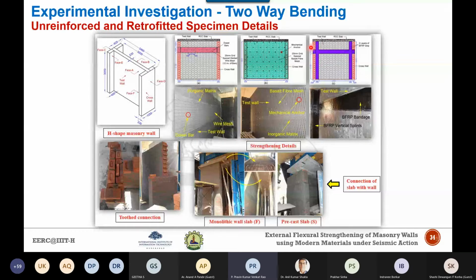So the vertical bands or belts are specially called splints. The vertical FRP which you are seeing is basically a splint, and the horizontal component of the strengthening reinforcement is specially called the bandage. Here you can see the BFRP vertical splints and then the BFRP bandage. In welded wire mesh and the basalt fiber mesh, we have used the inorganic matrix, cement sand mortar, whereas in case of the FRP, we applied this strengthening technique using epoxy resin and hardeners.